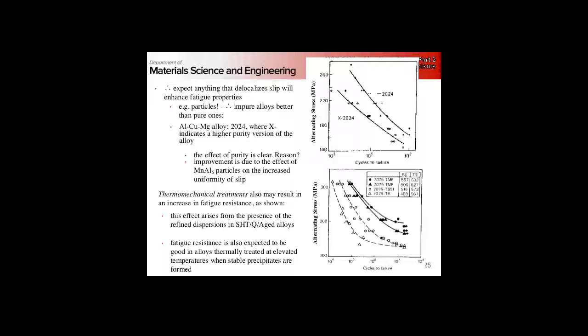Going through the notes, it's going to seem a little confusing, because we sort of say big particles are bad, big particles are good. Small particles are bad, small particles are good. It's all a matter of degree and subtlety and playing with things. This alloy design is not easy. And the same particle size in different aluminum alloys is going to give you a completely different response. So the big message is we want to delocalize slip. We want to make our deformation as homogeneous as possible to prevent fatigue failures.